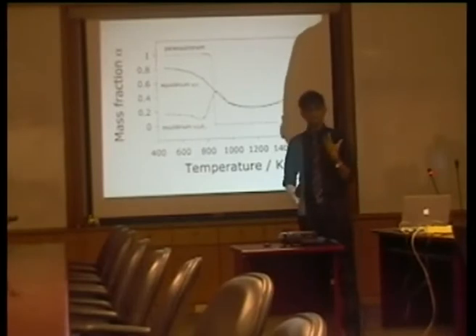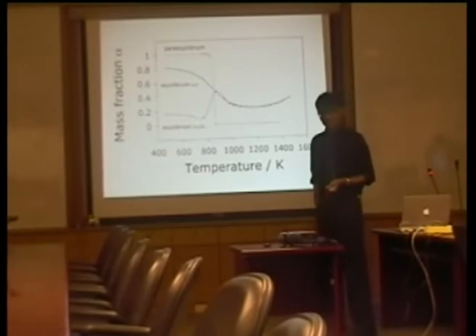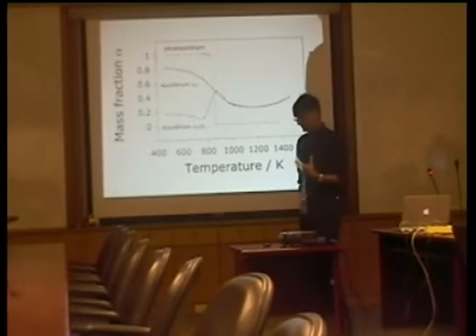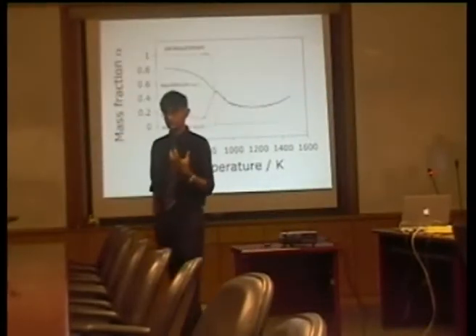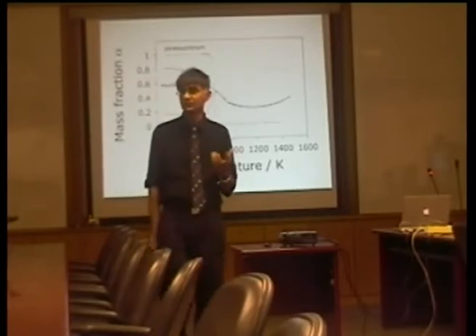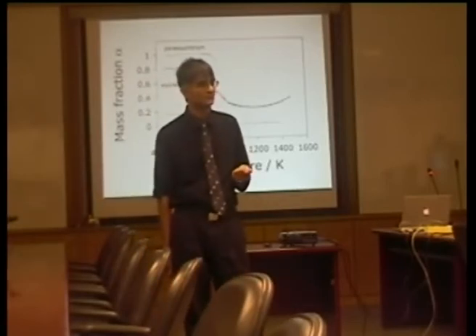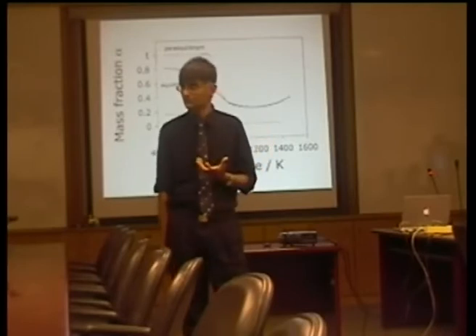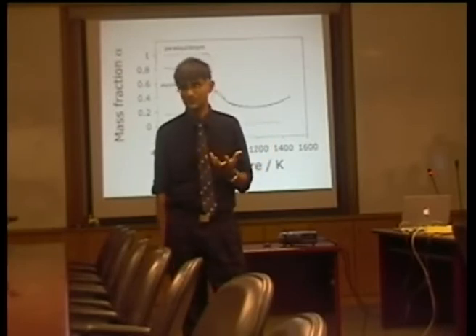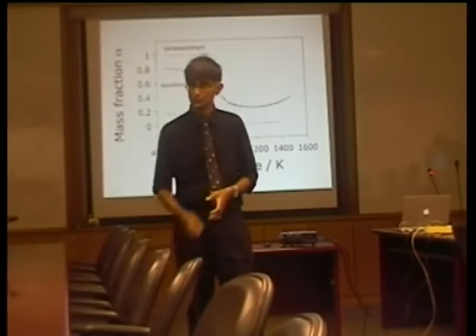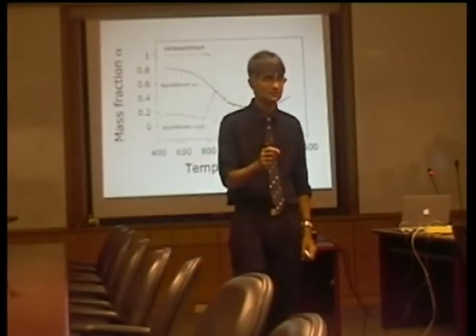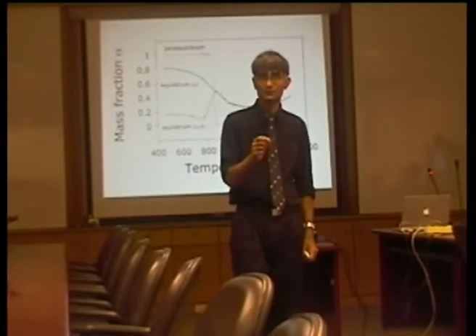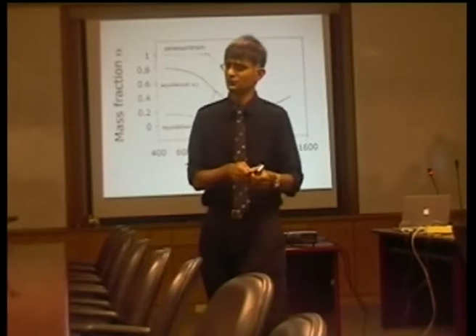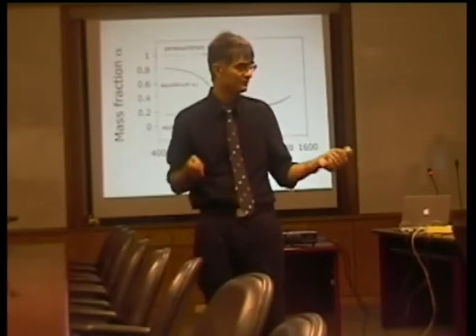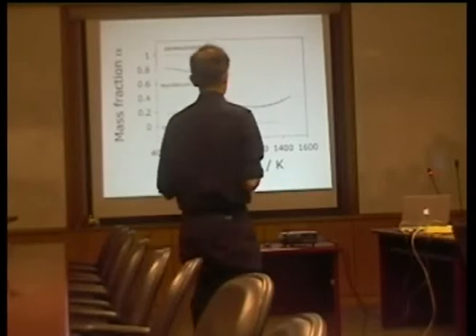Now, our results show that neither of them are correct. We are not following equilibrium. If we were following para-equilibrium, which is the real situation, then we should get 100% of martensite at room temperature. And experimentally, we've only got 57% of martensite. So there's something strange going on. According to thermodynamics, we should get 100% martensite, but experimentally, we've only got 57% martensite after doing a huge amount of work on the material. Only 57% of martensite. Why is that?